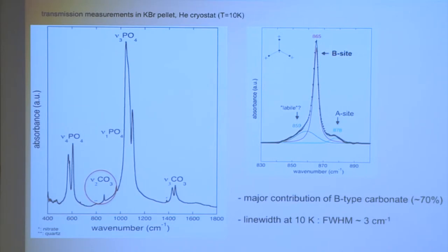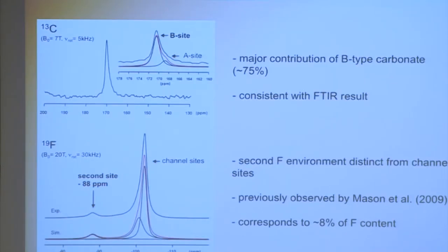And also a very interesting observation is that at low temperatures, the line width is really narrow, about a few centimeters to the minus one, which is a clear indication that carbonates occur in a defect site, but with a very well-defined geometry. So we can gain some complementary information from nuclear magnetic resonance spectroscopy, in which you can probe